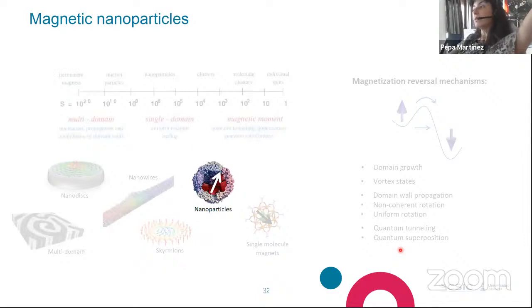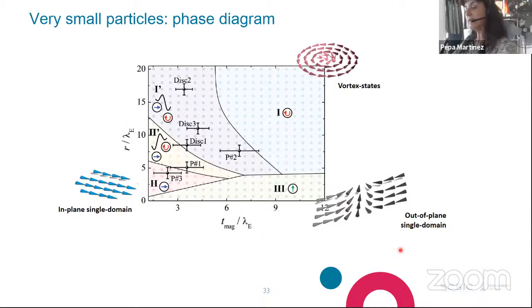Okay, let's go down to even smaller nanoparticles. And in this case, we wanted to understand a bit more which factors determine the ground state of magnetic materials when they have intermediate sizes. Let me explain this a bit more in detail. This is a phase diagram showing you the ground state of particles of this shape depending on their thickness that you see here on the horizontal axis and the radius that you see here in the vertical axis. For very, very, very thick particles with a small radius, that means nanowires, you will find an out-of-plane single domain. So a nanowire with the magnetic moment pointing along the z-axis.